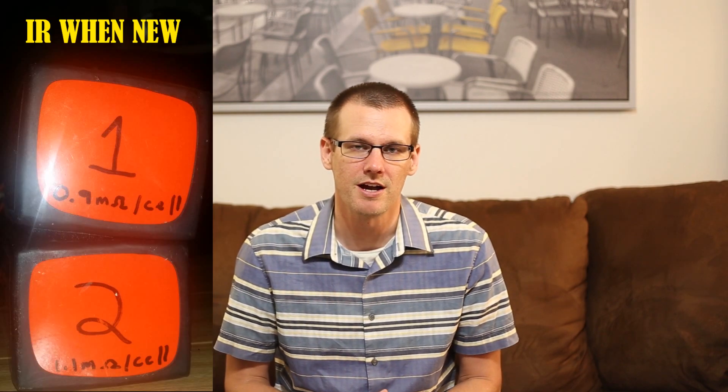I ended up looking at it just before running some of my RC vehicles for the season, and I was shocked that one battery pack was left at 90%. I hopped onto my charger, plugged it in, looked at the voltage of each cell, and all of them were quite high. I ended up discharging it to the proper storage voltage, and then a couple weeks later used it after I got all my RC models ready. Now the problem is that battery pack has a significantly higher internal resistance. I mark all my battery packs with the initial average resistance for each cell and place that on the end of the battery pack. This battery pack, however, had a very, very high internal resistance compared to the other.